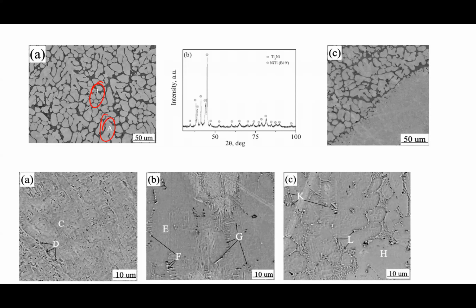occupies the interdendritic space. The EDAX analysis also shows that the chemical composition of this light gray phase is almost 52% of titanium and 48% of nickel, which corresponds to the titanium rich NiTi phase, because we have a titanium substrate. However, the dark gray phase consists of 67 atomic percent titanium and 33% of nickel, which corresponds to the Ti2Ni phase. This is almost confirmed from the X-ray diffraction analysis, showing the reflex of the B19 phase